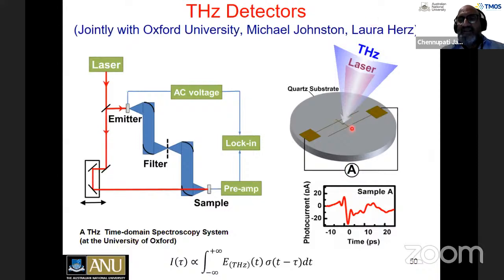She shines the laser light onto the nanowire, and then you generate electron-hole pairs. And then you come up with the terahertz pulse. The electric field of the terahertz pulse is the one which separates the carriers between the two contacts. You can measure photocurrent as a function of time. If you can measure the current as a function of time, you can get the information about the electric field of the terahertz pulse and also the conductivity of the material which we're dealing with.